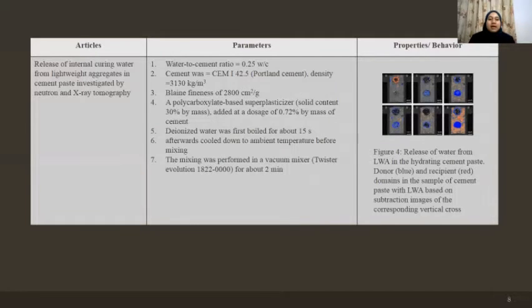In this project, I have found 3 articles that are directly related to the objectives of this project. The first article is Release of Internal Curing Water from Lightweight Aggregates in Cement Paste Investigated by Neutron and X-ray Tomography. The parameters in this article are a water to cement ratio of 0.25. The cement used was Portland cement, CEM I 42.5, with a density of 3,130 kg per cubic meter. The Blaine fineness is 2,800 cm squared per gram.